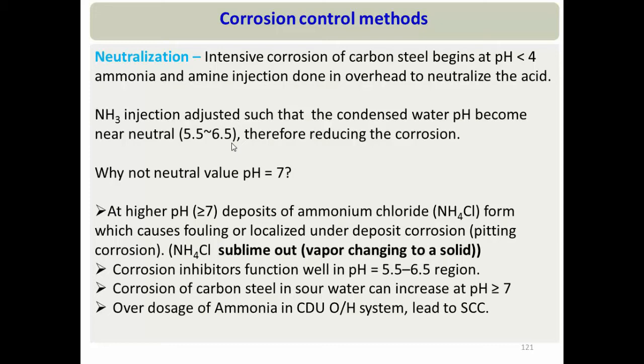However, we should not dose ammonia in very high amounts or raise pH above 7. At higher pH, ammonia reacts with hydrogen chloride to form ammonium chloride, which sublimates — converting from gas phase directly to solid phase. The solid deposits can foul overhead lines or exchanger tubes, and if electrolyte remains under the deposit, under-deposit crevice corrosion and pitting can occur.